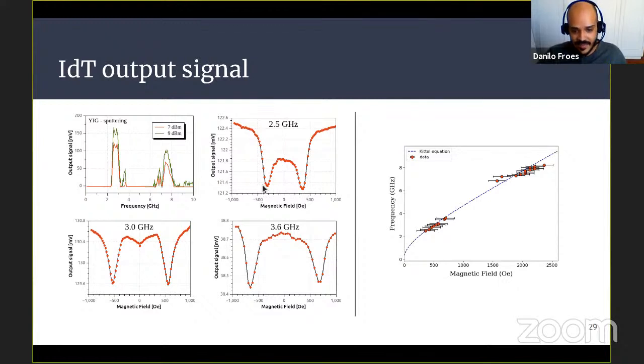So we have these dips in the output signal, these absorptions at some magnetic fields. I plotted this magnetic field as a function of the frequency, so a frequency versus magnetic field dispersion, and we actually got these results, these red results. We didn't know exactly what to do with that, what it meant.